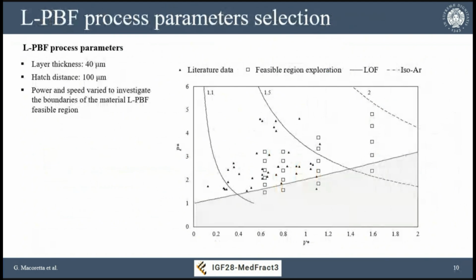Based on this model, I started defining a wide set of L-PBF process parameters, keeping a constant layer thickness of 40 microns and a constant hatch distance of 100 microns, varying only the power and the velocity.